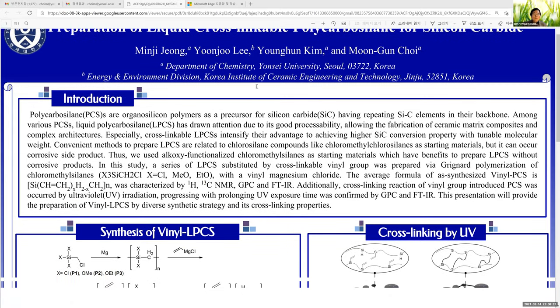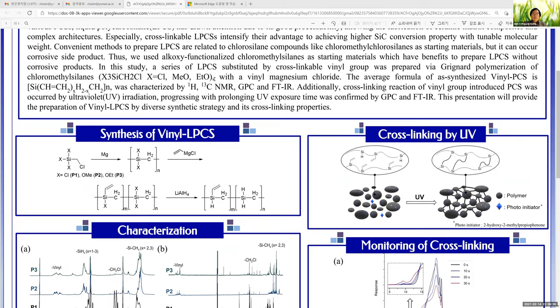A convenient method to prepare liquid polycarbosilanes uses chlorosilane compounds like chloromethyl chlorosilanes as starting materials. But it can produce corrosive side products. Thus, we use alkoxy-functionalized chloromethyl silanes as starting materials, which have the benefit of preparing liquid polycarbosilanes without any corrosive side products. In this study, a series of liquid polycarbosilanes substituted by cross-linkable vinyl groups was prepared by Grignard polymerization of chloromethyl silanes with vinyl magnesium chloride.